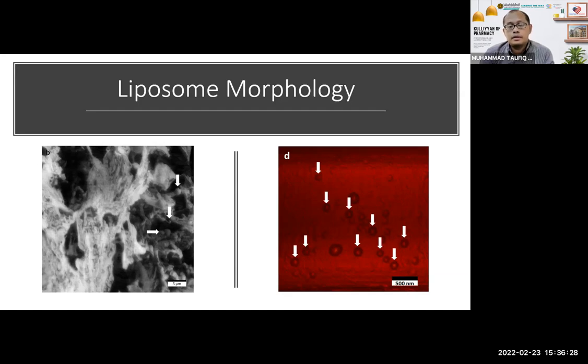Now, when this happens, the liposome will become smaller. So this has to be monitored using the Zetasizer. So I did various concentrations of trehalose, and then I see which one is affected by the amount of trehalose, and which one can actually be freeze dried. Because, for example, let's say a concentration of 300 millimolar to 500 millimolar of trehalose is good for the size, meaning that the size doesn't change compared to if you don't put any trehalose at all, meaning that the liposome can still maintain the water content and everything.